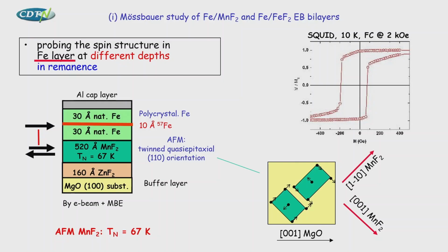We started studying many years ago iron-manganese fluoride and iron fluoride bilayers. These are model systems for exchange bias. And then we applied iron-57 probe layers with this. We have grown samples with these fluorides. The important point is that in these fluorides the antiferromagnetic order happens only at low temperature, below 70 K, let's say. Then we have grown samples putting 1 nanometer of iron-57 at different positions, and we have measured in remanence in the standard CEMS.